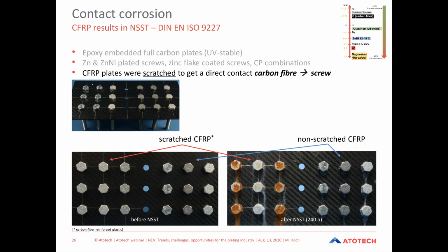The difference between scratched and non-scratched boards can be seen at the bottom of the slide. Screws screwed into non-scratched panels benefit from the insulation of the epoxy and show almost no corrosion, which is here after 240 hours salt spray, while those in scratched panels, those ones here, already corroded considerably.